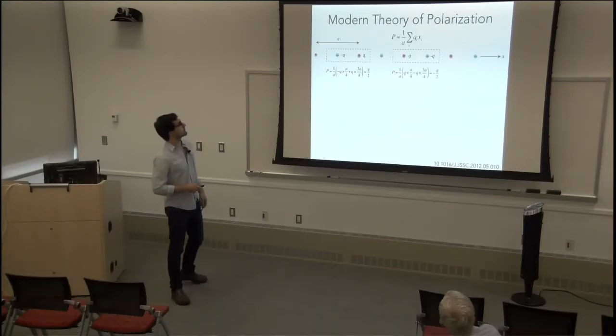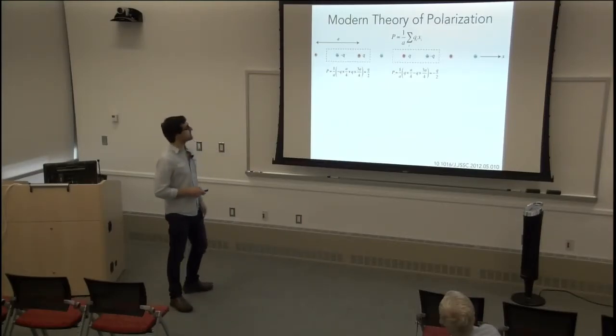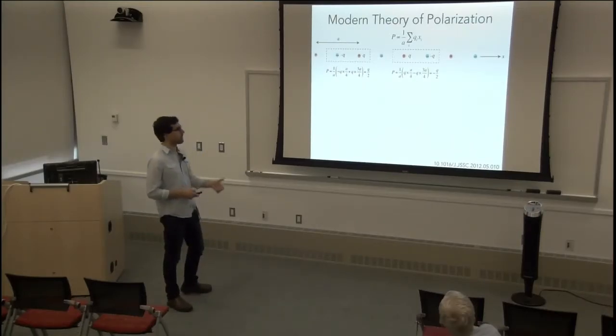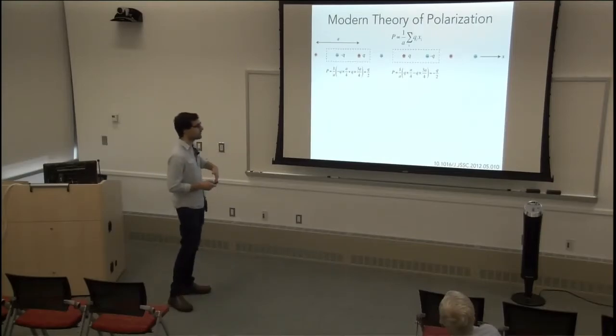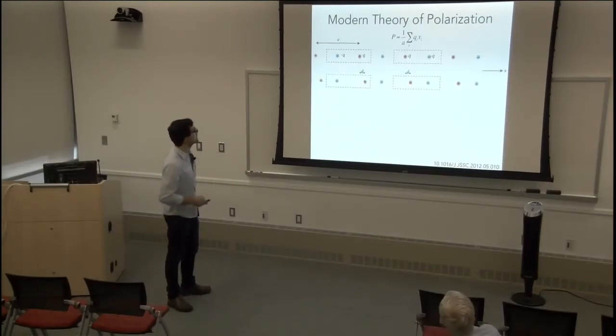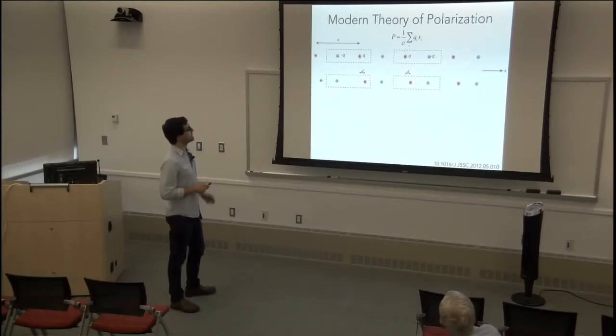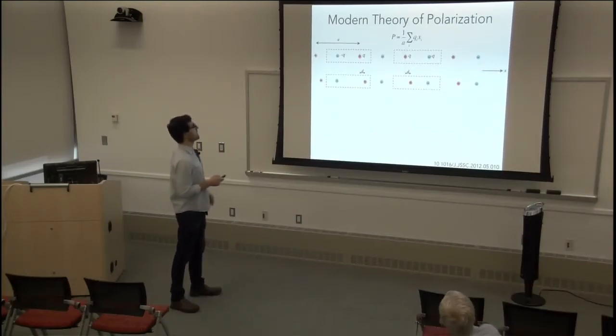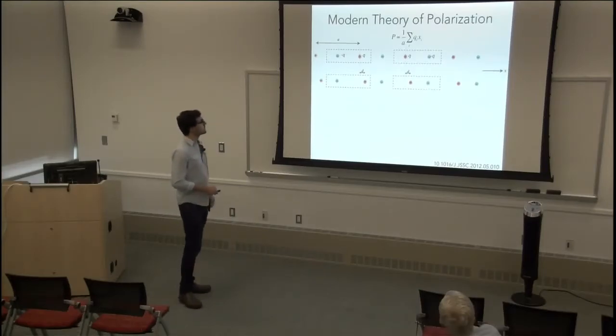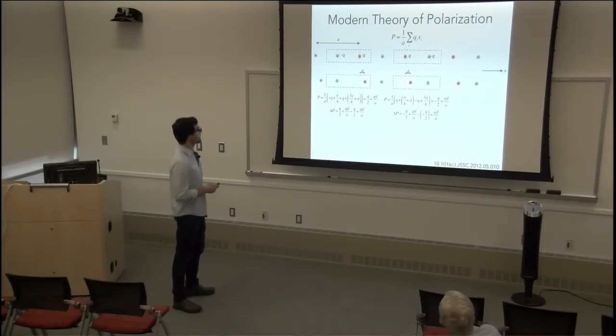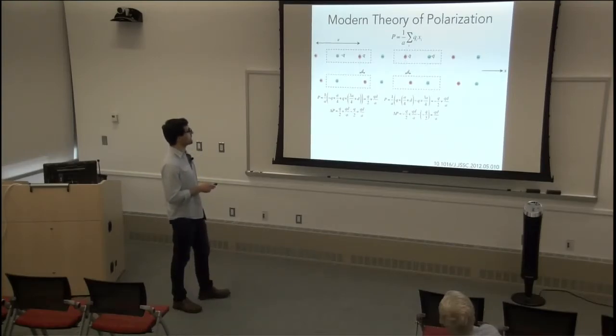The way one should think about polarization is not as a static situation, but as a dynamic process. And that's really what's happening in experiments. In experiments, they move from one state to the other state, and then look at the difference. So now I make some sort of perturbation in my system, let's say through an applied electric field, and now my positive charge moves towards the right by a distance of d. If I now calculate P, I end up getting in both cases a term that's charge QD over A.